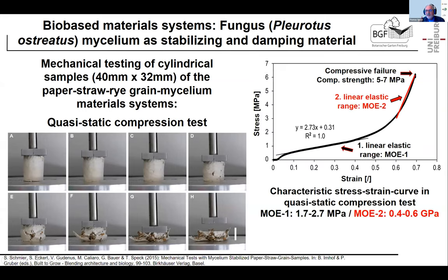And if you look at the data, then it's really interesting. You see first, it can be compressed tremendously. It can be compressed nearly by 70%. A strain of 0.7 is relatively huge. You have two linear parts, which we called linear part one, modulus of elasticity one. And then it's compacting. So it's strain stiffening, compression strain stiffening. Then you have a linear part two where we can calculate the modulus of elasticity two. The modulus of elasticity one is between 1.7 to 2.7 megapascal. The modulus of elasticity two is between 0.4 to 0.6 gigapascal.